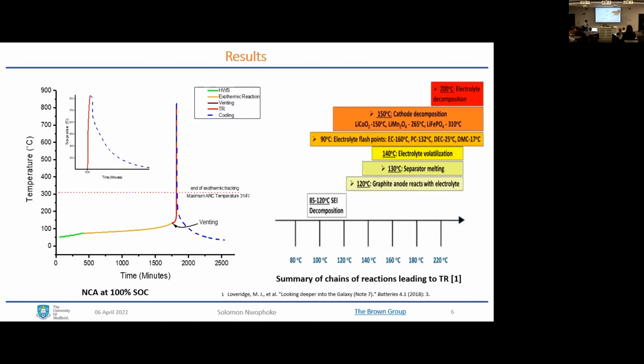A lot really happened within this region, and that's why I added this picture to give a hint of what goes on. The onset is the point where the first exothermic reaction commences within the battery, and that is decomposition of the solid electrolyte interface, which is a coverage between the anode and the electrolyte, and then it progresses to decomposition of the electrolyte. So all of that happened within this orange region, and then there's a venting here.